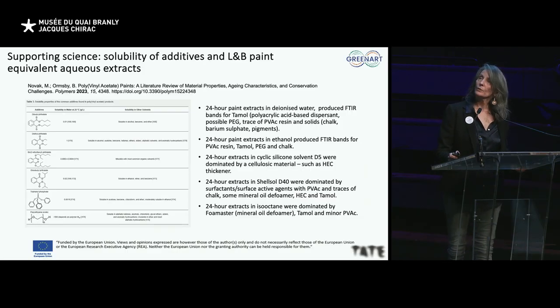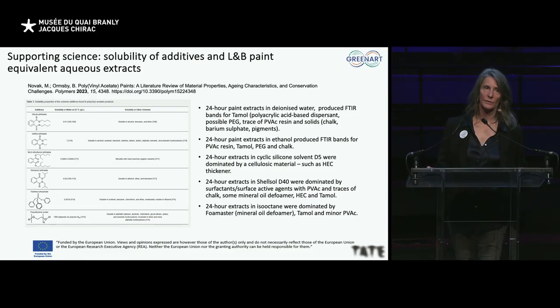So some of the things we're looking at in the papers was the solubility of some of these additives because of the risk of extracting them in cleaning treatments, and we also did your classic 24-hour extracts that scientists love to do, including myself, to see what kind of materials might come out of the paints, while acknowledging it's nothing like touching the surface with a beautiful sponge-like water-based system. It did tell us, and tell me in particular, that the additives are very similar to those that are vulnerable to extraction with acrylic paints.